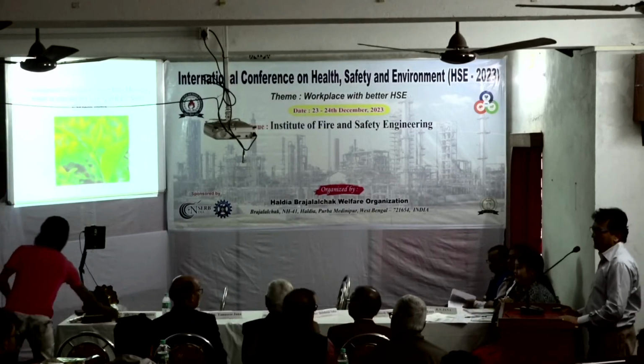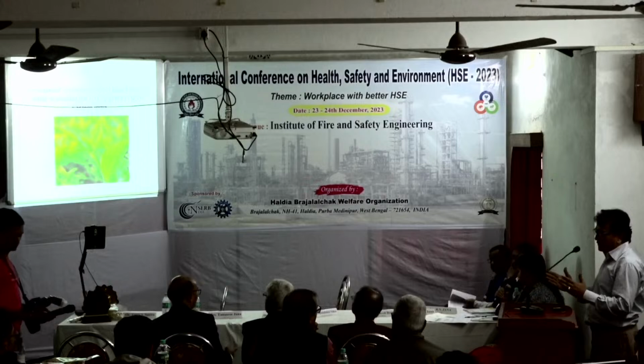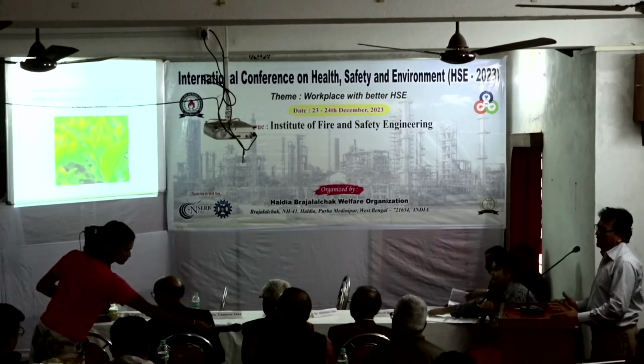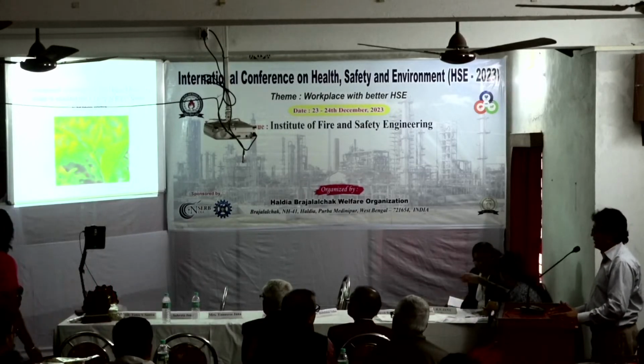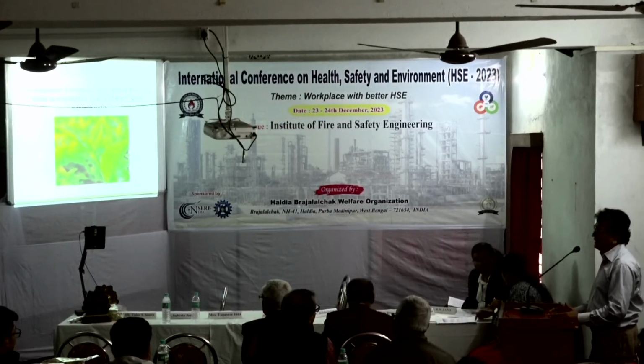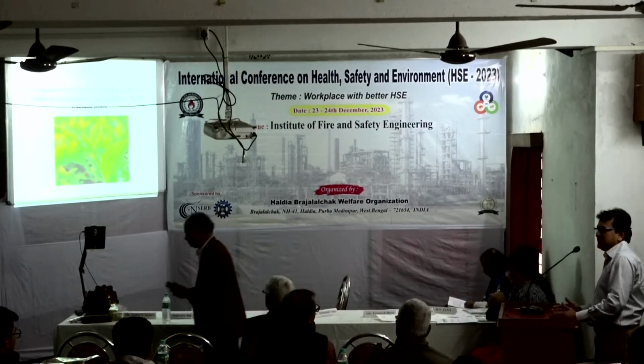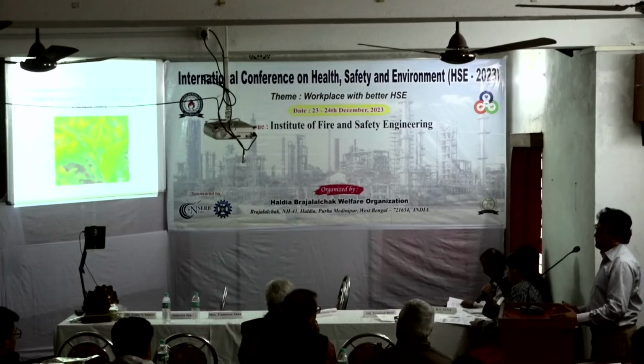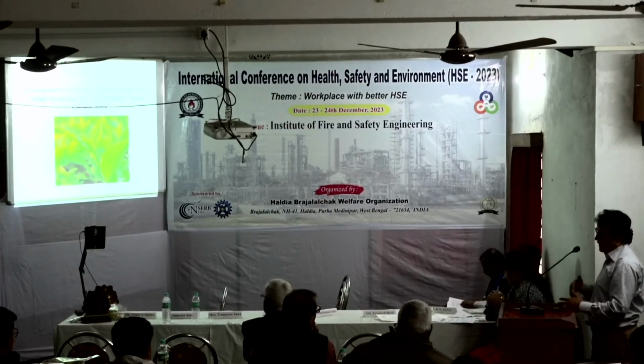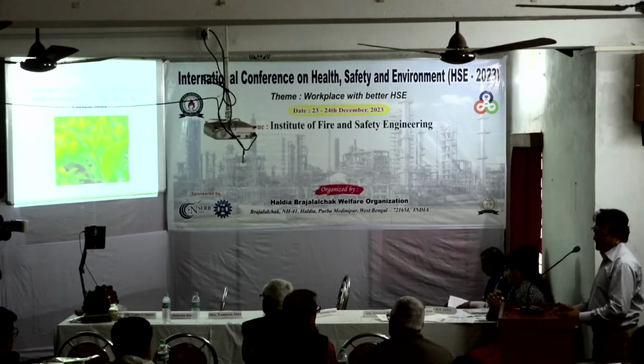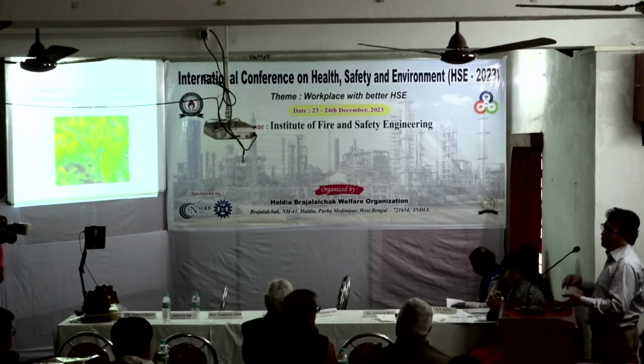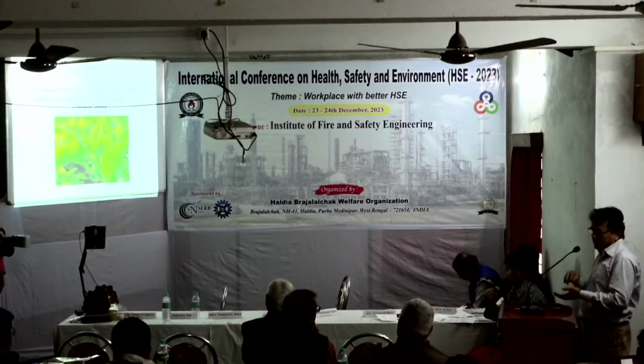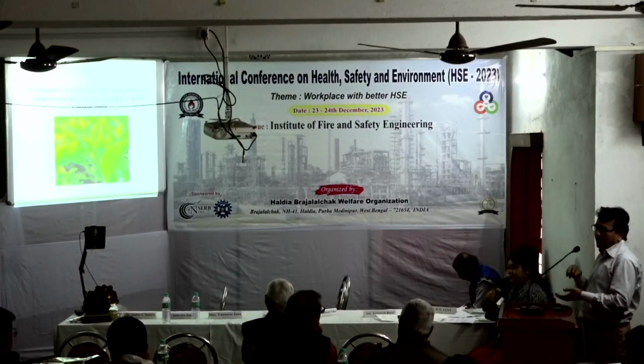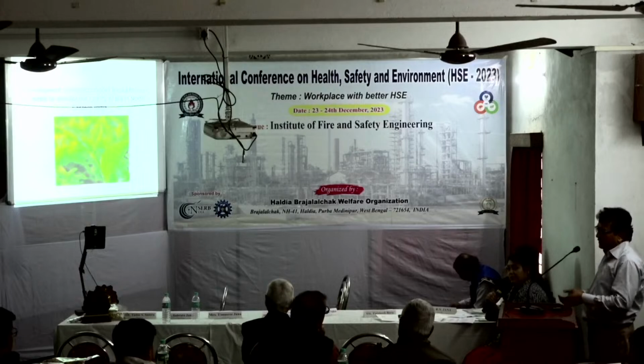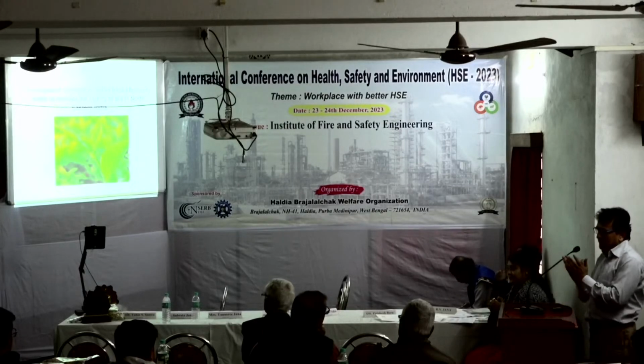In transformer, we developed 1 to 100 ppm, but for most of the NTPC persons, their detection limit is maximum 25. But our sensor senses up to 100 ppm. From 1 to 100 ppm moisture, we sense. If you want more than that, we also tailor this material, actually tailoring the porosity by adding some pore former materials like buckyball, means fullerene, carbon nanotubes, graphene. So we developed the porosity, like conical pore, cylindrical pore.